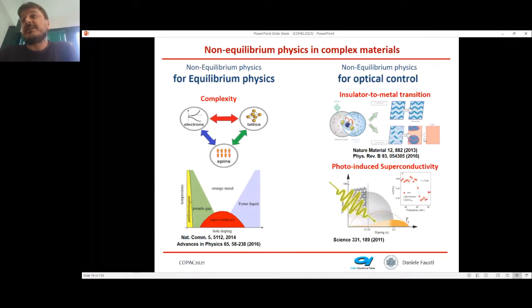And in those studies, which are now a little bit dated, we could show that it is also possible with an electric field to trigger the formation of a superconducting state. And this is a little bit at odds with our intuition about thermodynamics, because what the light generally does is drop energy into the material, but rather than inducing a disordered system, it triggers the formation of a low entropy phase. So clearly the electric field is doing something else. It's not just leaving energy into the system.